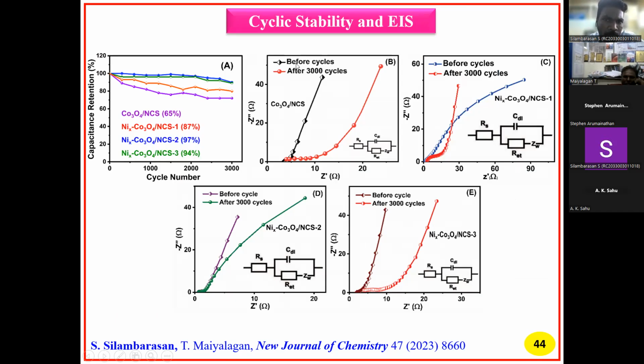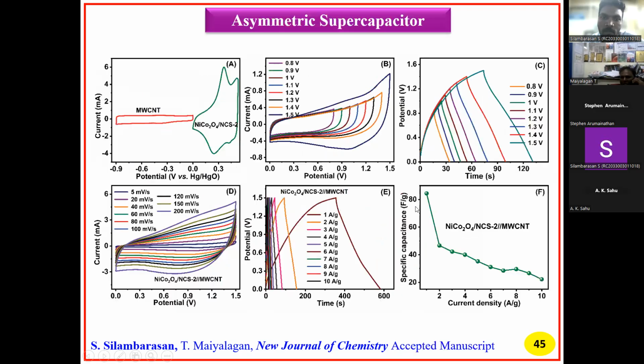Next, the impedance. Before cycling and after 3000 cycles, we measured the impedance over a frequency range of 1 millihertz to 10 kilohertz. So overall, sample 2 has less resistance because of its higher conductivity compared to the other samples. So next one, the asymmetric supercapacitor.